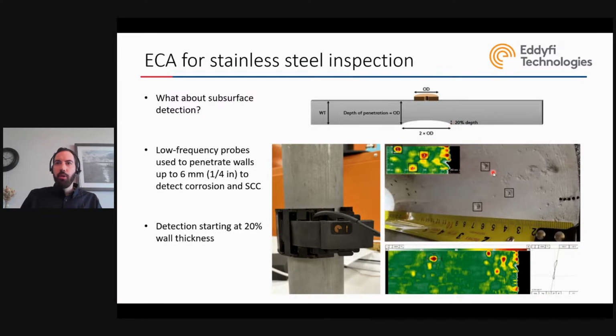So here in this example, you have this same bracelet that we wrap around this section of pipe, and on the inside, we were able to see visually that you have these corrosion wall loss 1, 2, and 3 that we could detect very well on the C scan. So again, this is a green background, number 1, 2, and 3. You notice that they are mirrored because you're looking from this side, but the indications are on this side. So it's like looking at a mirrored screen where your 1, 2, 3 are in the opposite direction, just because this is a far side.